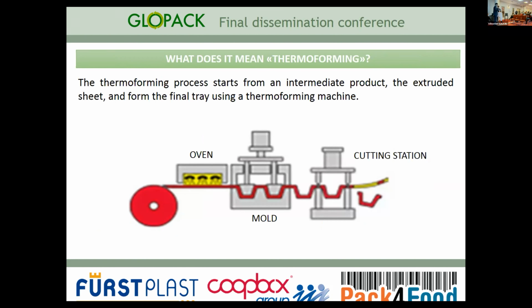The thermoforming process, here is a scheme of it, usually consists in the processing of rolls of material, typically standard material like PET and PS. These rolls are heated in an oven so that the material becomes softer and it's possible to thermoform it. Thermoform it means that you have to use a mold to give the final shape to the material so that you have the tray. After that, you have a cutting station so that the single tray is separated from the total foil, so that you will have the single tray.